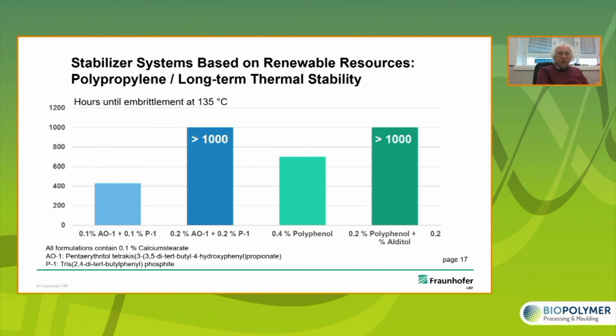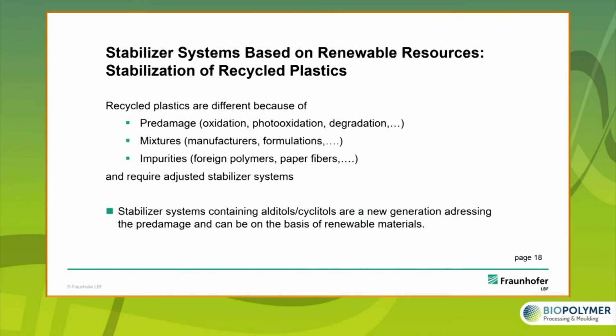In the usual combination out of AO plus P1, we reach 0.1%, 400 hours until embrittlement. If we double the concentration, then we have 1,000 hours. If we add the same concentration of polyphenol, then the result is worse than compared to the classical combination. But if we use the new system consisting of polyphenol and alditol, then we see in the long-term thermal stability the classic properties. We can keep the classic properties or even outperform them.